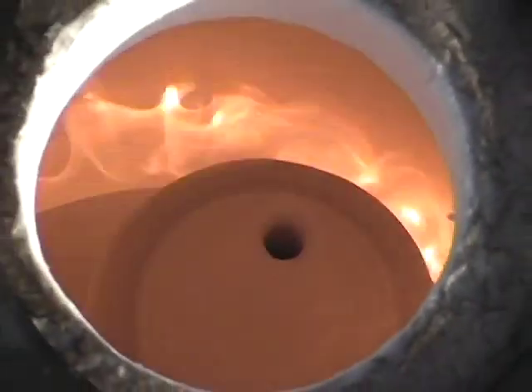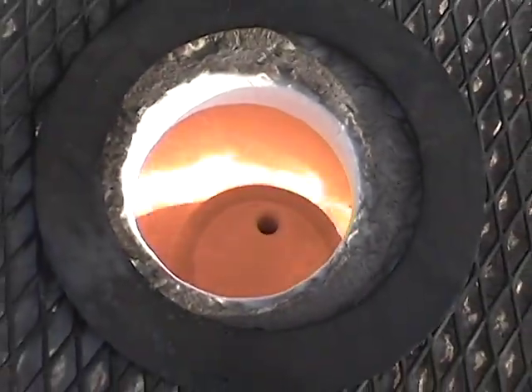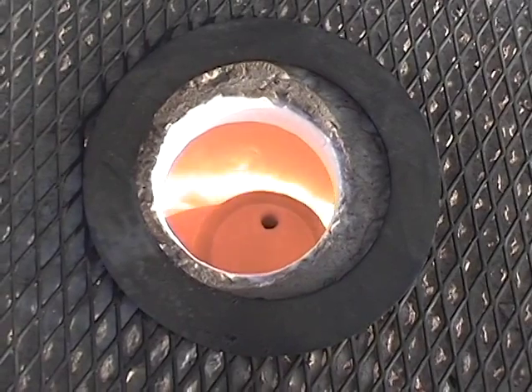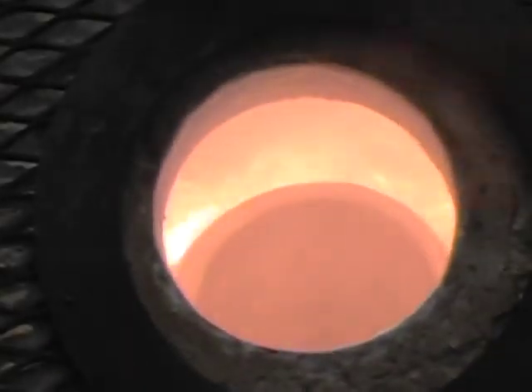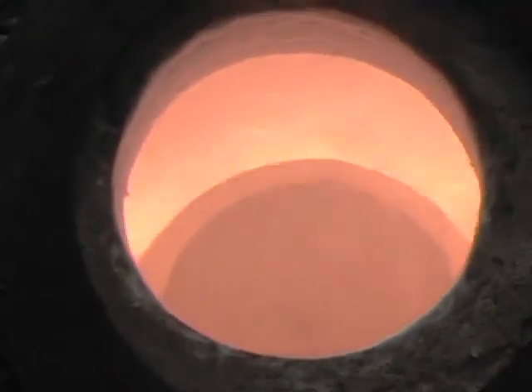If you'd like to be more exact about your temperatures, you can always rig the Claydog Raku Kiln with a pyrometer for exact measurements. After about 15 or 20 minutes in high fire, you'll notice that the foaming glazes have laid back down onto the piece, and the piece will actually look shiny like it's been dipped in water or wax. This is an indication that the glazes have actually matured, and they're almost ready to take out of the kiln.